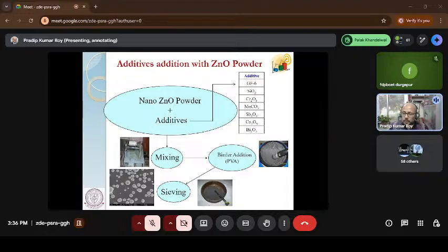So they produce the nano zinc oxide powder through some spray pyrolysis method, and they added all the additives I talked about, like silica, chromium, manganese and antimony. All these additives are mixed with the nano zinc oxide powder, because 96% of it is nano, the rest 4% may not affect that much. So they mixed it properly.